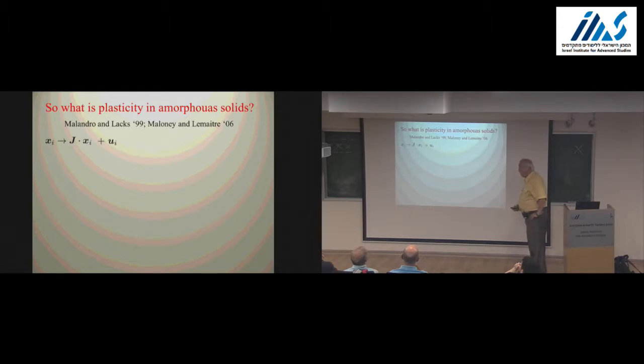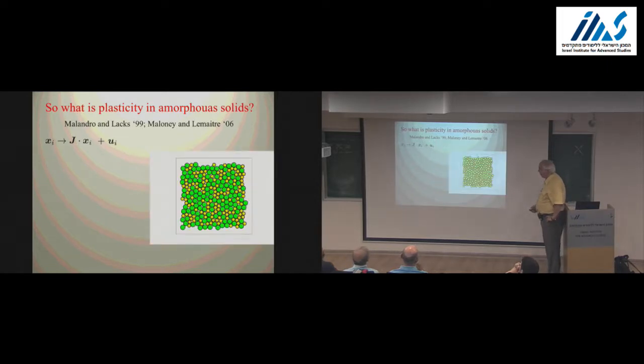But when you have a crystalline solid, if you do an affine transformation, that is it, because you just stretch some of the bonds, you squeeze others, and the system is still in mechanical equilibrium. Not so in a glass, and you have what we call a non-affine response. To show this, it's a film that Idan prepared for me how many years ago? Maybe 10 or 7 or something.